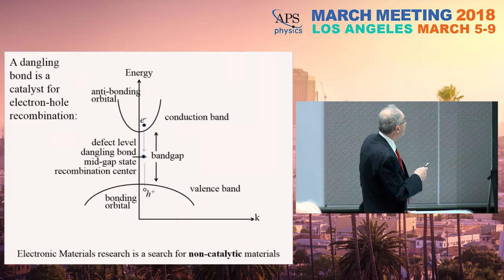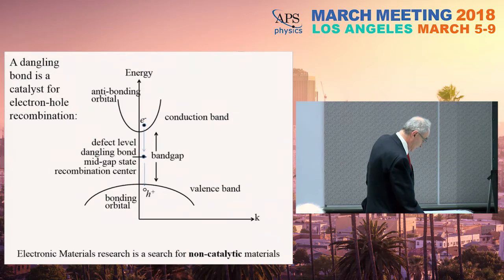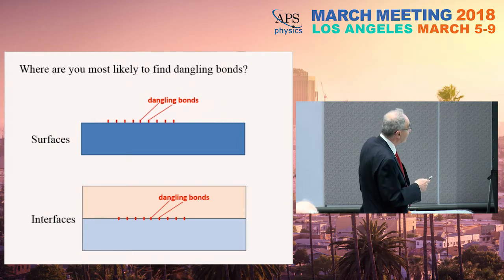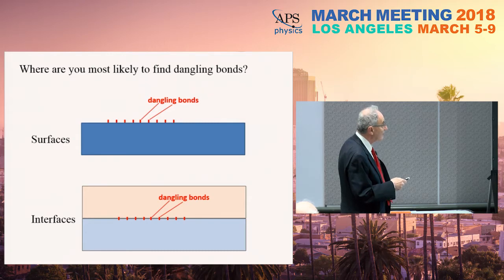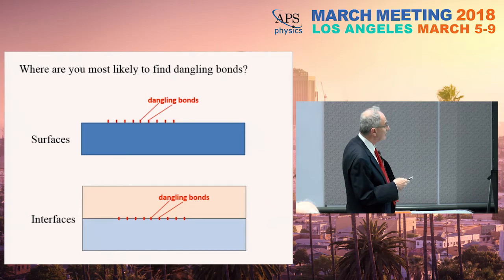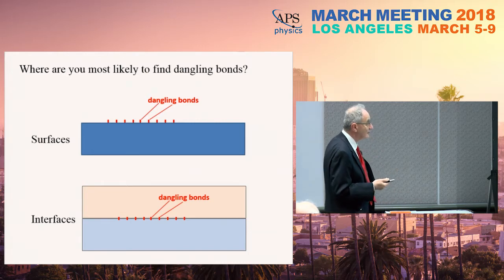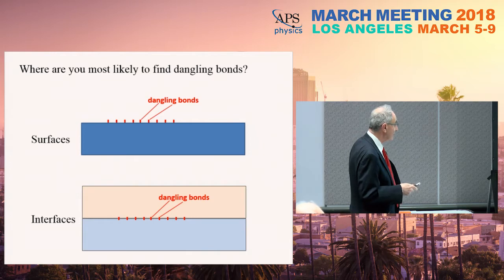It's a catalyst, but a bad one — for something you don't want to happen. So we have to prevent dangling bonds as best we can. Typically what happens at surfaces is the biggest problem in semiconductors. If you have a fabulous semiconductor that is very pure and structurally perfect, it still has all these dangling bonds on the surface, so the surface is effectively completely loaded with defects relative to the volume.